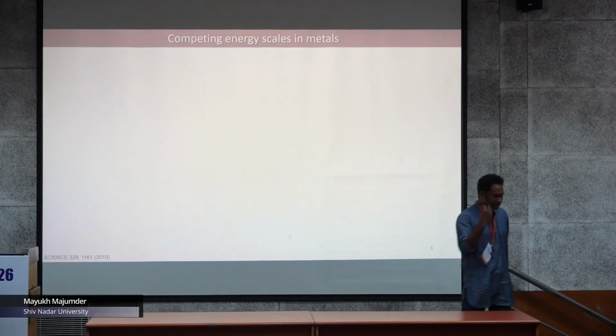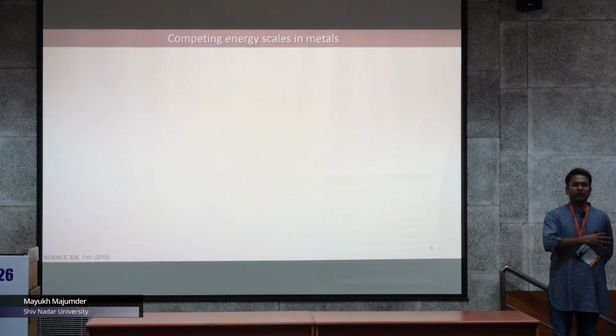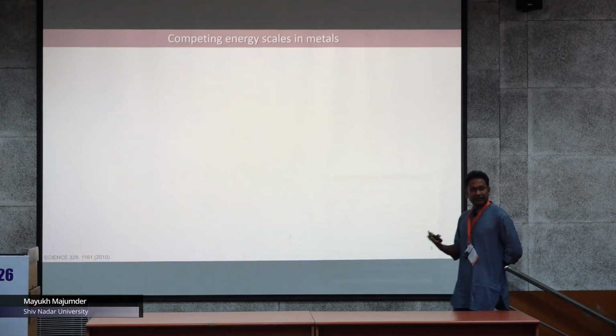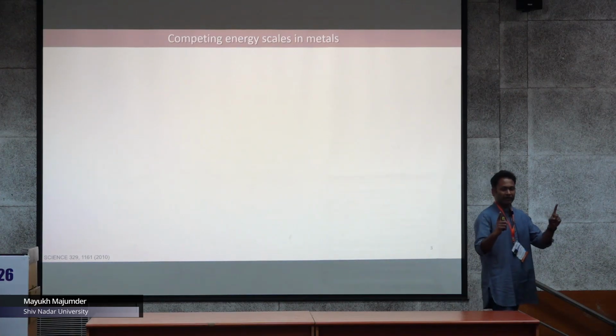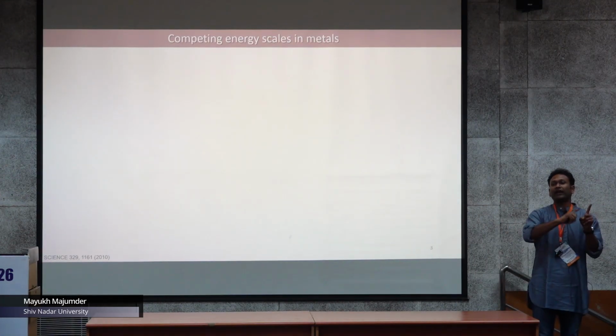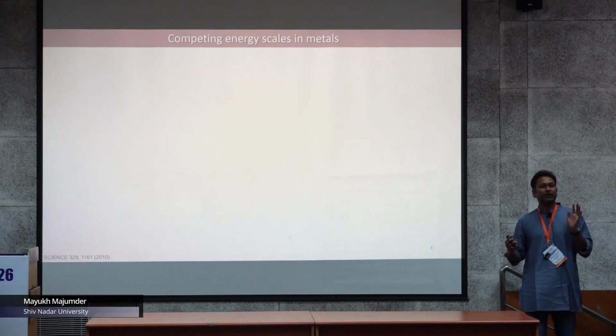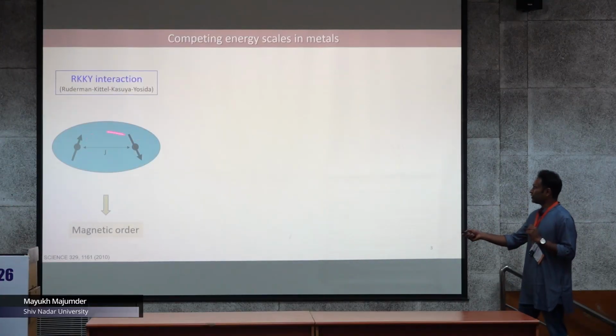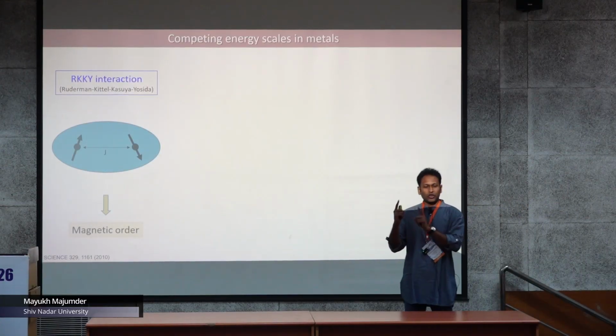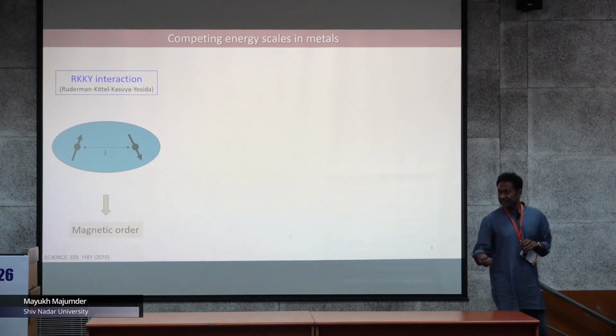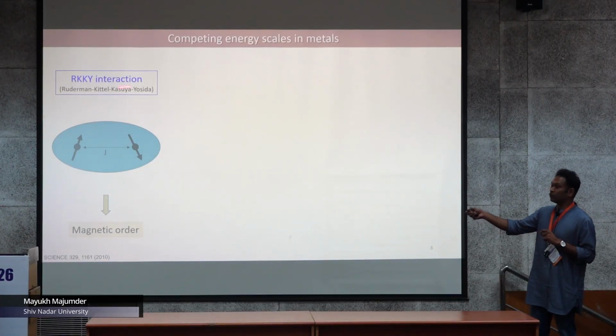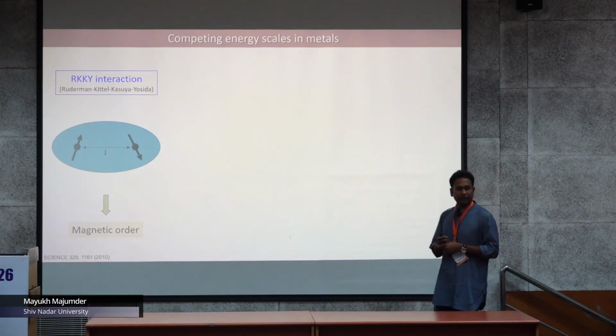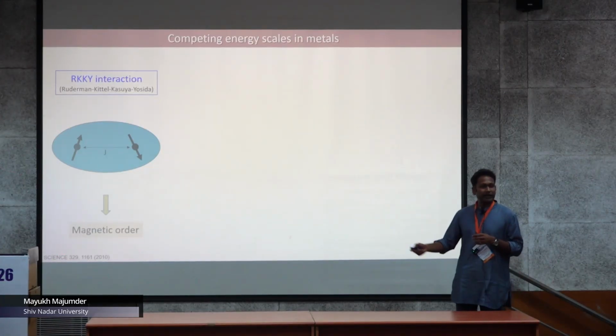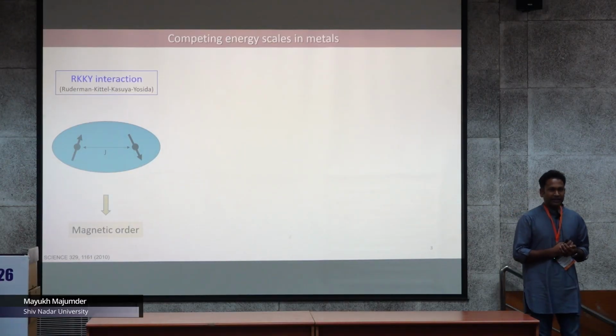Now, since in metals you have a huge number of conduction electrons, the local moments interact with each other via the conduction electrons, some kind of a super exchange interaction. If you consider that the coupling between the conduction electron and the local moment is J, then that kind of interaction is known as RKKY type of interaction, and that gives rise to a long range magnetically ordered ground state in case of a metal.